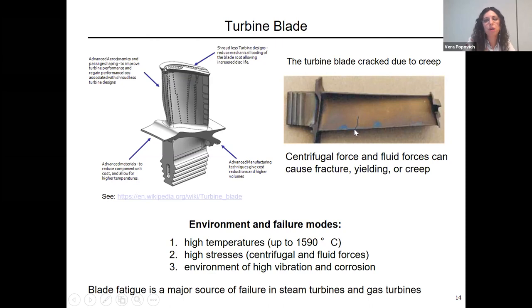But for creep, quite often the failure analysts always find that something initiates the crack, yeah? And quite often it's either a fatigue crack, or in recent cases of some failure of aircraft, this is related to sulfide corrosion or oxidation on the surface. And that's why, as we will see later on, these turbine blades are coated, so they have a thermal barrier coating. Besides the temperature protection, for sure, it's also to address the oxidation and corrosion resistance of the material.